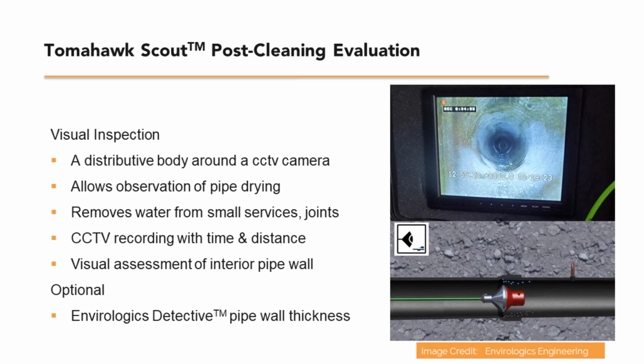Following cleaning, the Scout camera is deployed to record CCTV video inside the cleaned pipe. The Scout camera is propelled using airflow, again generated with a vac truck. The pipe wall is also dried with the process, as the pressure drop associated with air accelerating around the probe helps evaporate water from the pipe wall. The same process helps remove water from small services and joints.